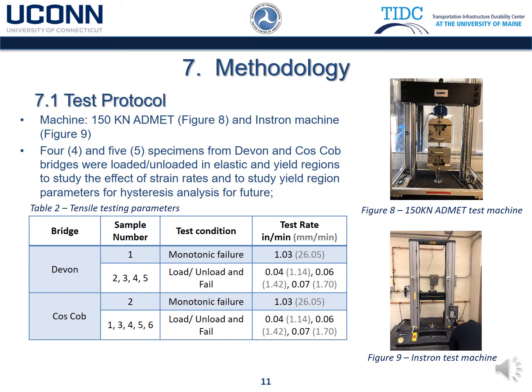Methodology. Test protocol. Two testing machines were used for the tensile test. Figure 8 shows the 150 kilonewton ADMET machine, and Figure 9 shows the Instron machine. On Devon Bridge, 1 specimen was subjected to a monotonic failure following the ASTM test rate specification. The remaining 4 specimens were loaded and unloaded at different test rates and stress levels through the failure. This process allows us to understand the effect of strain rates and study the yield region. A similar test protocol was adopted for Cos Cob Bridge, with 1 specimen with monotonic failure and the remaining 5 specimens loaded and unloaded through failure. Table 2 shows the summary of the test parameters.